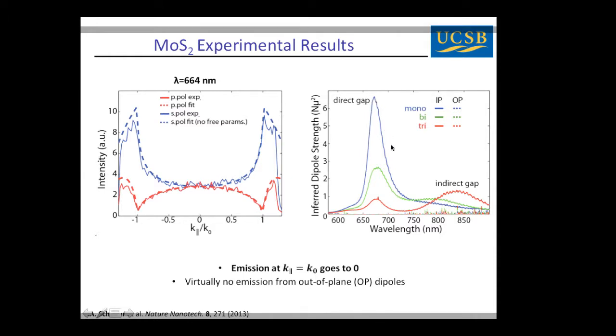So we were able to demonstrate directly that in a monolayer of MoS2, we have only in-plane oriented dipoles, or we separate the excitons within a layer, not surprisingly. But as we go from monolayer in blue to bilayers in green and trilayers in red, there's an indirect gap feature here, which we thought might be related to charge transfer or interlayer excitons. We can show definitively that it's not, okay? That this indirect gap feature still corresponds to an in-plane dipole moment.